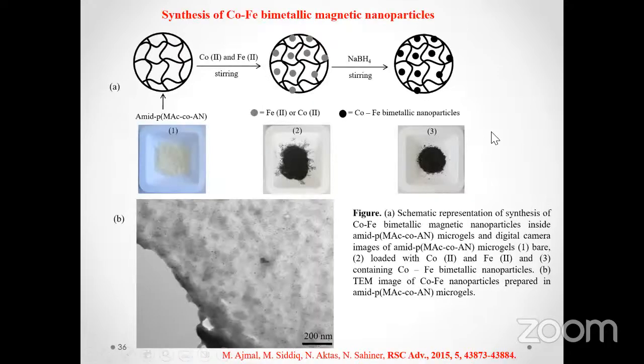So this is the further modification of this hydrogel system, that we have used this hydrogel system for the synthesis of bimetallic magnetic nanoparticles by using cobalt and iron as the precursor metals, and we have prepared cobalt iron bimetallic nanoparticles in this hydrogel system. And the indication of the formation of the nanoparticles can also be observed without using any high resolution technique, that when we have the pure hydrogel system, then it was off-white colored, and when we loaded a mixture of cobalt and iron ions, then it was converted to dark brown color, and when these metal ions were reduced into the metal nanoparticles, then jet black color was observed.